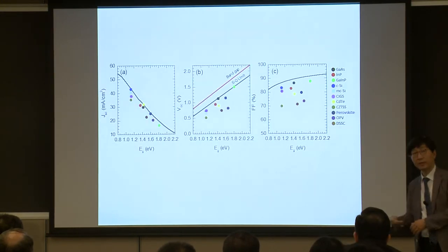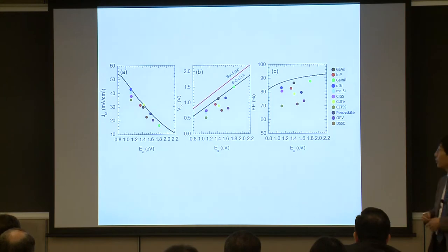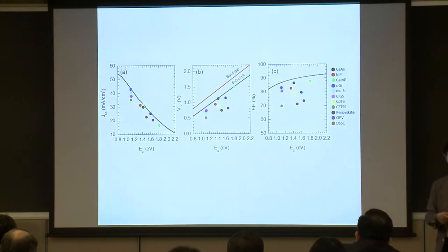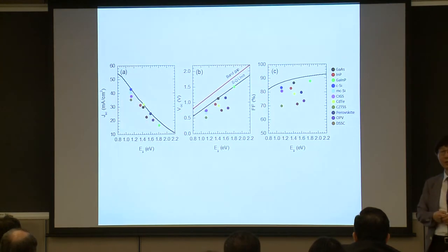If you break down to see what's going on about the current, voltage and fill factor, the perovskite here is the dark blue color. Here is 1.6 eV, and then the photocurrent density already approached the Shockley-Queisser equation limit. But the open circuit voltage is slightly lower than this SQ limit, and the fill factor. Actually, for 1.6 eV, the fill factor theoretical value is about 0.91, but still lower than the SQ limit.